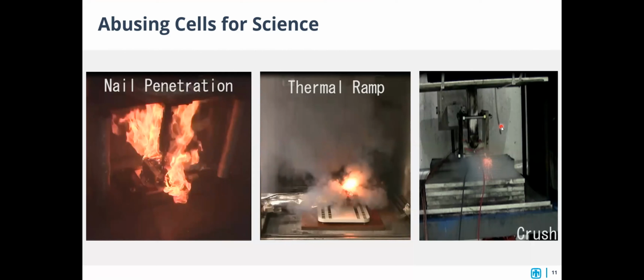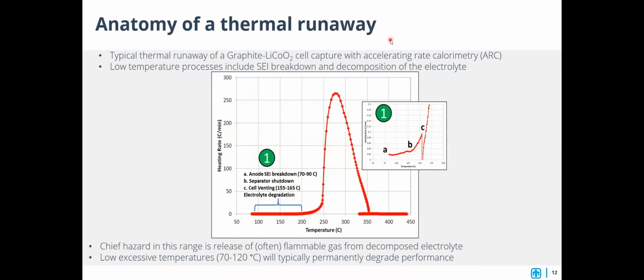So the issue, especially when it comes to heating, is a term that's already been discussed today, which is thermal runaway. I think the best way to start describing thermal runaway is through looking at accelerating rate calorimetry, or ARC, tests of a battery chemistry. What you're looking at in this curve is the actual temperature of the cell and the heating rate per unit time of the cell. It's important to note that this temperature is being generated by the cell itself. Once thermal runaway starts, all temperature is being generated by the cell itself. That's the proper definition: the cell is unable to lose heat as fast as it's gaining it. And thermal runaway is actually a series of reactions.